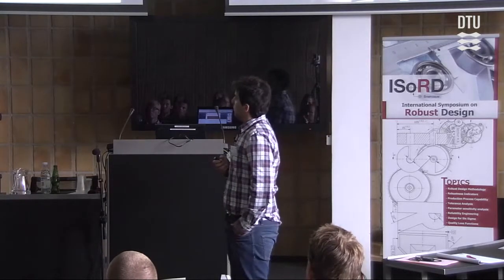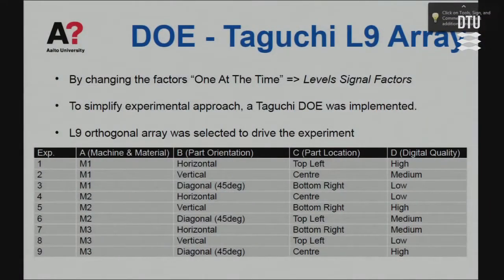So how we did that: we implemented a Taguchi experiment, and I did a randomization using an L9 orthogonal array. If I had used, for example, full factorial, it is an exponential relationship, 3 elevated to 4, which means I had to make 81 experiments. And if I want to include the variance of the experiments, you need to multiply by the number of times you repeat the experiment. And if you include the variance of the measurement, imagine how big an experiment you can have. But with the randomization that L9 orthogonal arrays allow, or bigger orthogonal arrays, you can make a simplification.